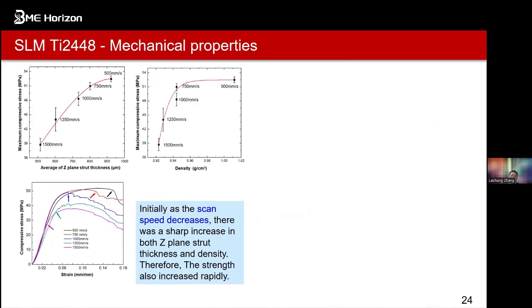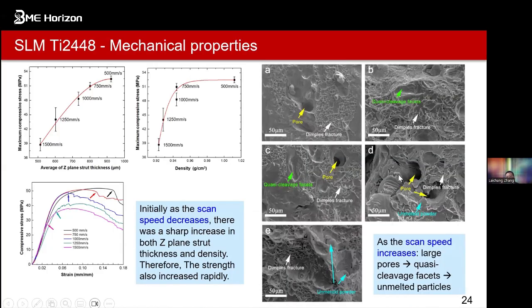And of course, you can see there are some parameters. The scan speed of these things will also change the layer thickness of these kinds of structures. The density will change and also the mechanical property will be changed. So that's why from here, we still need a lot of knowledge to optimize the structures. Because when the structure is not good, they will produce a lot of holes inside, and then we make this part break much earlier than predicted. That's what we call premature failure.